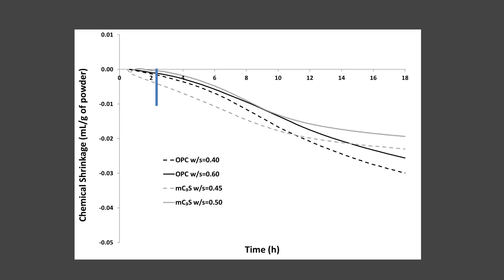Also, you might say, whoa, maybe what you're seeing is chemical shrinkage. That's where as the cement reacts, it actually sucks up water. And some people have thought that that might form these voids. Ladies and gentlemen, there's no chemical shrinkage going on. That's what this plot shows. Here is the amount of chemical shrinkage. And there is at 12 hours, 14, 16, 18 hours. But at our magical two-hour time period, not much chemical shrinkage going on.